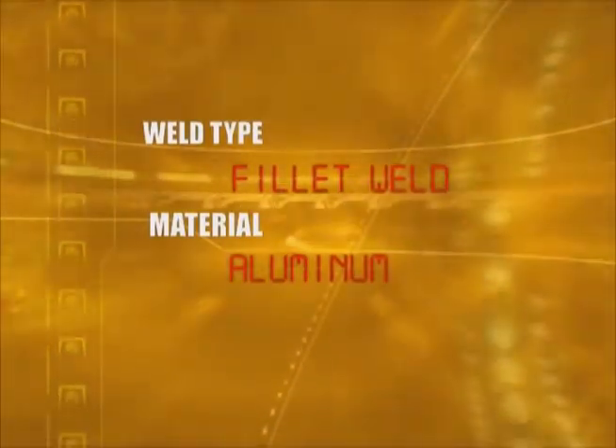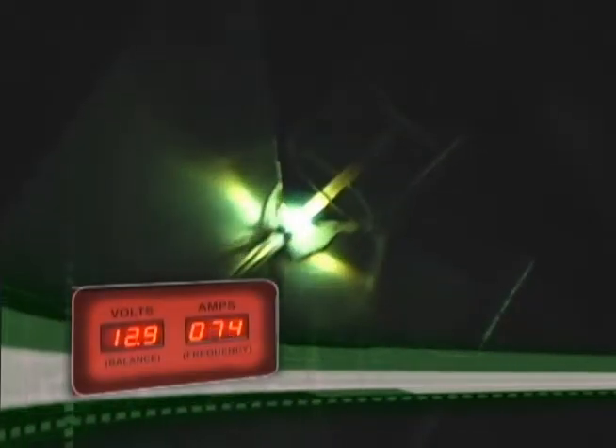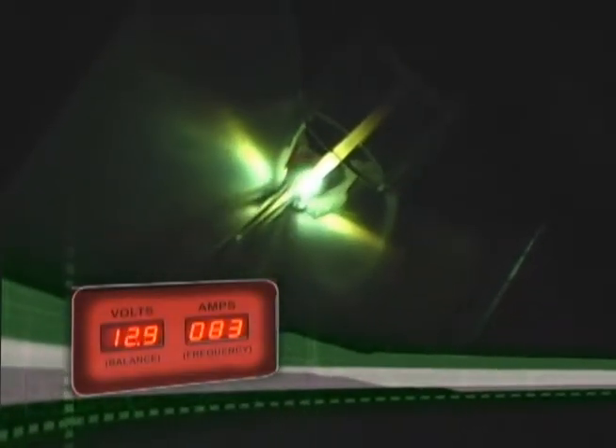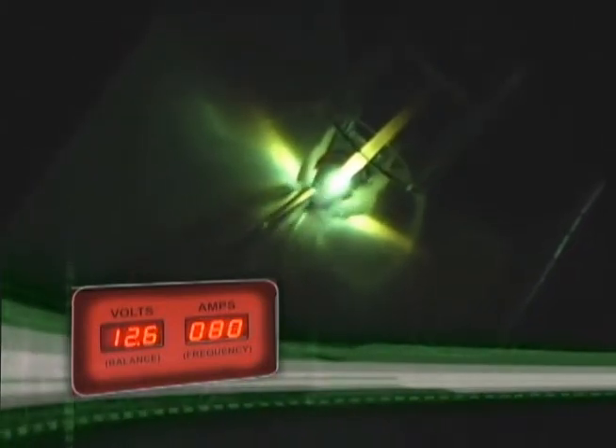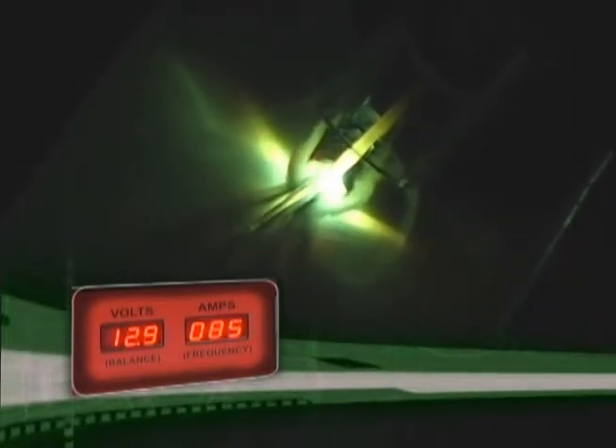Once you have mastered the aluminum lap weld, it is time to move on to the fillet weld. Again, remember to tack the panels. You will concentrate the heat on the lower panel and let the filler wick into the upper panel. Make sure you dab the filler into the molten puddle.